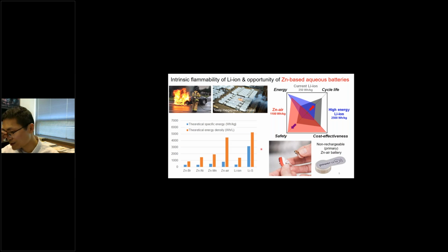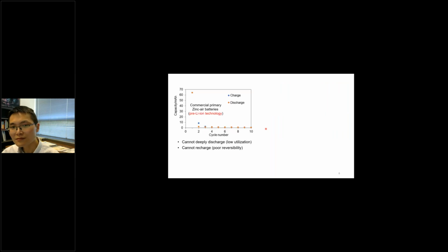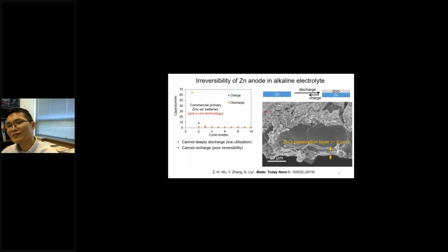So our research was to improve the rechargeability and utilization so that we can have a promising rechargeable and safe battery. The commercial zinc batteries are not rechargeable. They can discharge, but then they become dead. So we did a lot of research to figure out the mechanism, why it dies, and how we can address this problem. This schematic shows the formation of zinc oxide on the surface as a discharge product. As this covers the fresh zinc, it stops electrolyte from coming in. Even if you have fresh zinc under it, it cannot further react. And also zinc oxide is insulating, so it's very difficult to convert it back to zinc metal.